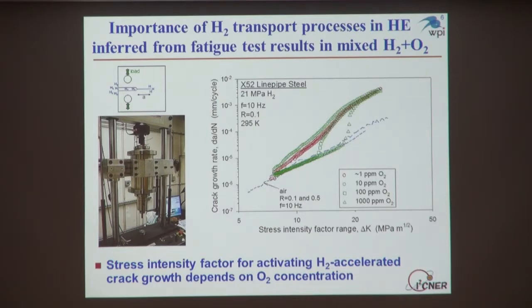And what I'm showing you here with the data that we measure from these types of experiments is the crack growth rate, the amount that the crack advances per load cycle. And you can just think of this as the stress range, so the difference between the maximum and minimum stress we're applying to the material. And what I'm showing you here with the dashed line is the rate of the crack growth in the absence of any environmental effect. So this is the rate that we would measure, let's say, in air.